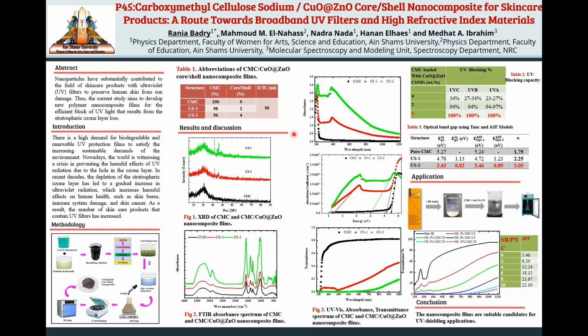Thus, based on the obtained results, we used this film containing 4 weight percentage of core shell nanoparticles to enhance the blocking of one of the sunblocks present in the Egyptian market. We diluted the sunblock in deionized water, and then we added different concentrations of our polymer nanocomposite to this sunblock. And then we studied the transmittance of this sunblock polymer nanocomposite. We found that the transmittance of the pure sunblock decreased sharply with increasing concentration of our polymer nanocomposite until it reached 100% blocking, which is a very good result.